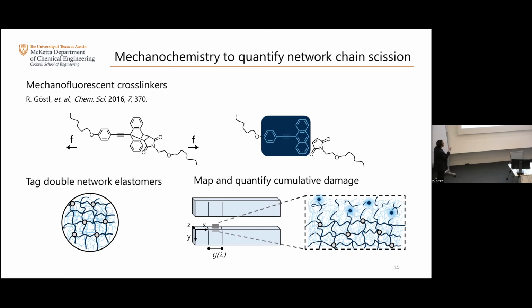So when I incorporate these probes only on the filler network of my multiple network elastomer, I can then probe groups that have been broken and that are activated under a fluorescent microscope in my specimen after it fractured. So the name of the game is, let's make these fluorescent cross-linkers, put them in the multiple networks, and then fracture our material, put it under a confocal microscope, and then we can map and quantify how much damage I had during the fracture process, okay?